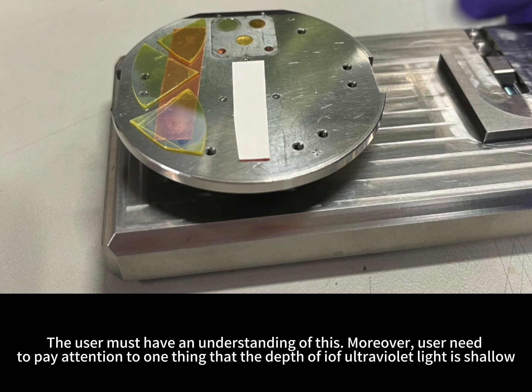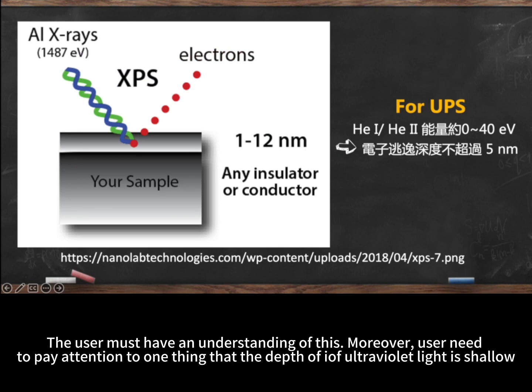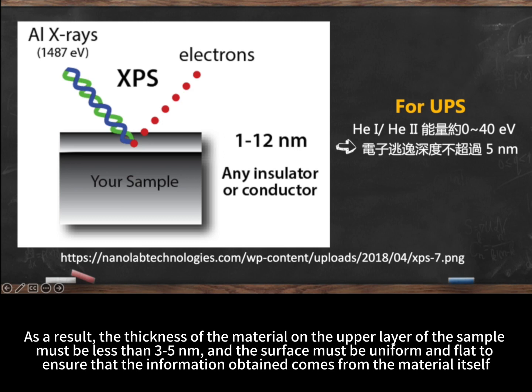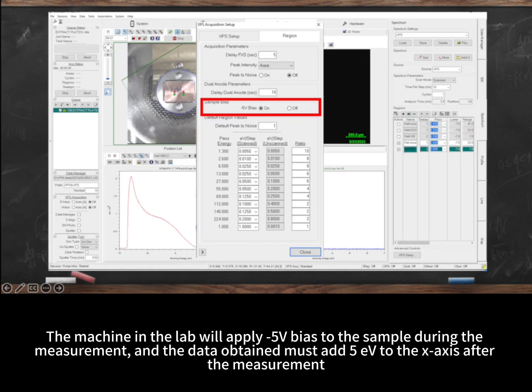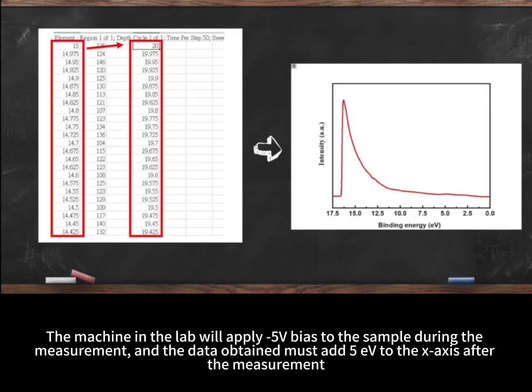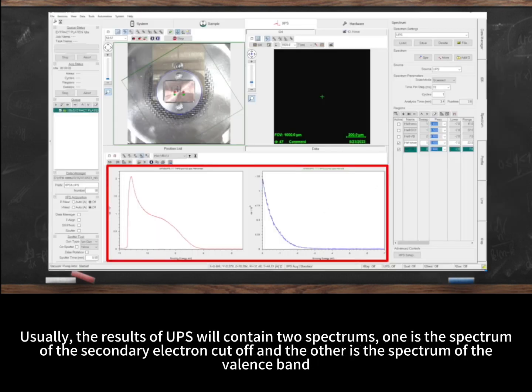Moreover, users need to pay attention to one thing: the penetration depth of ultraviolet light is shallow. As a result, the thickness of the material on the upper layer of the sample must be less than 3 to 5 nanometers. And the surface must be uniform and flat to ensure that the information obtained comes from the material itself. The machine in the lab will apply a -5 V bias to the sample during the measurement, and the data obtained must have 5 electron volts added to the x-axis after the measurement.